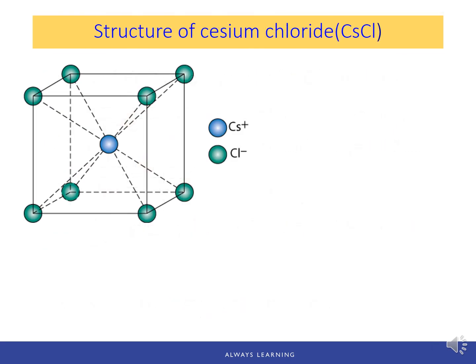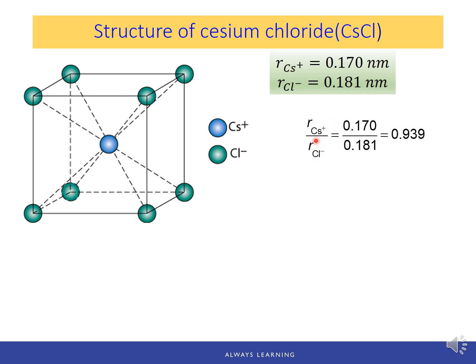Another common AX compound structure is the cesium chloride structure. Here you're looking at a unit cell for cesium chloride. First, let's check the ionic radii. The radius of the cesium ion is 0.170 nanometer, and the radius for the chlorine ion is 0.181 nanometer. So the ratio of RC over RA is 0.939, almost 1. That means the sizes of those ions are very close.